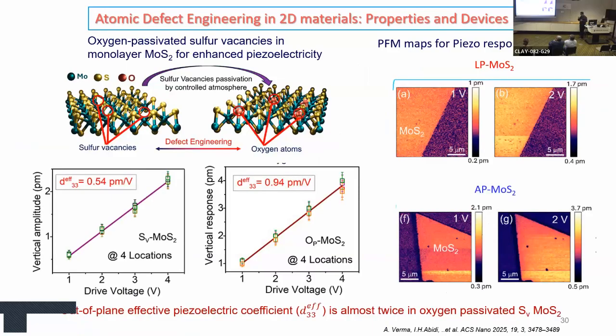This is also useful. In this case, we have to passivate the sulfur vacancies if we want to exploit the piezoelectric properties of MoS2. What we observe is that once we passivate these sulfur vacancies with oxygen, the piezoelectricity enhances. That is because once you have sulfur vacancies, the surface is more electrically charged, basically an n-doped surface. But once we dampen them with oxygen passivation, the piezoelectric coefficient enhances about 2 times for the MoS2.